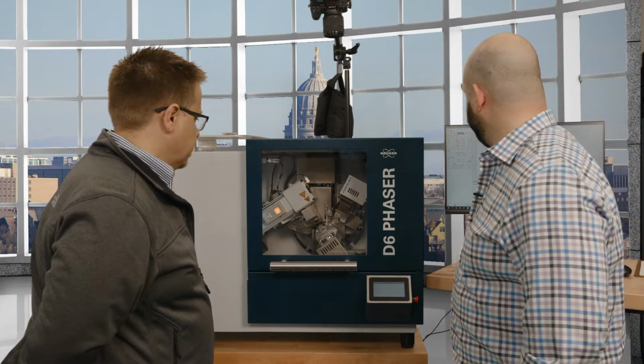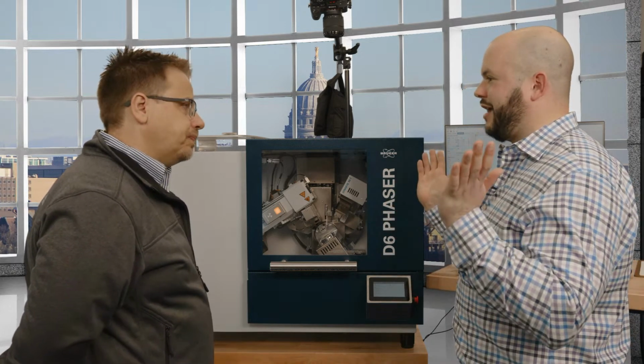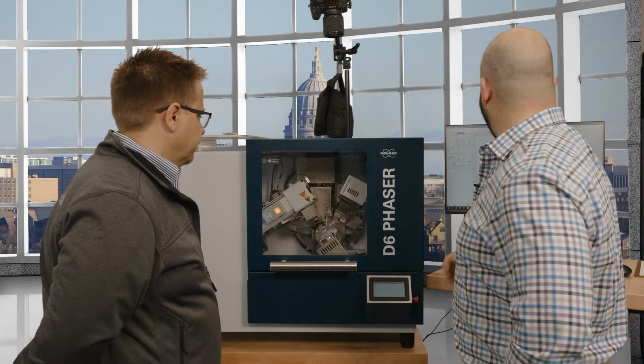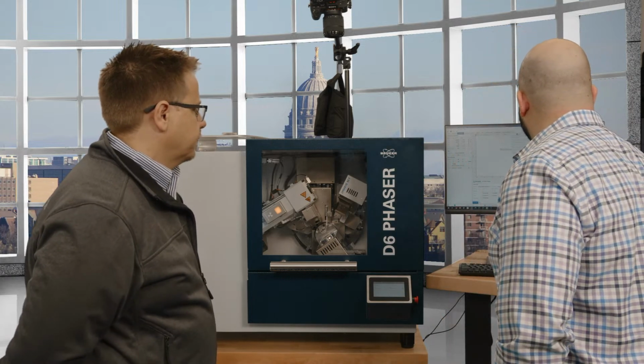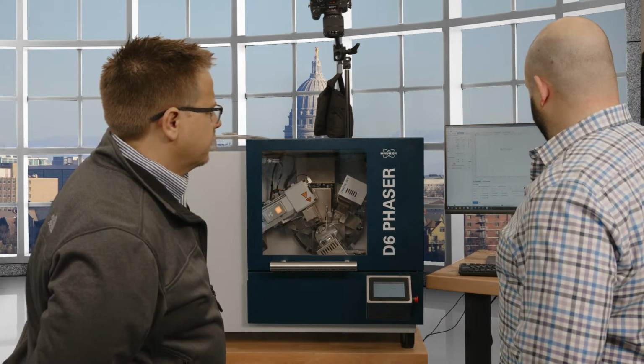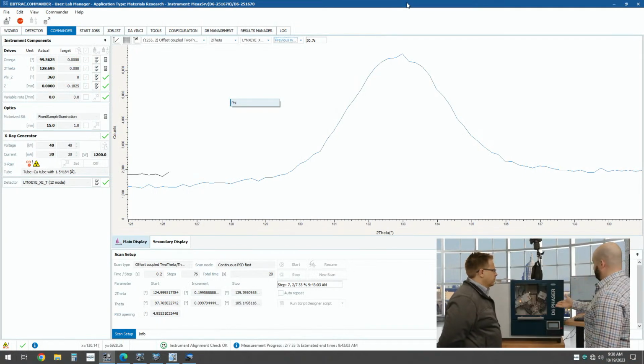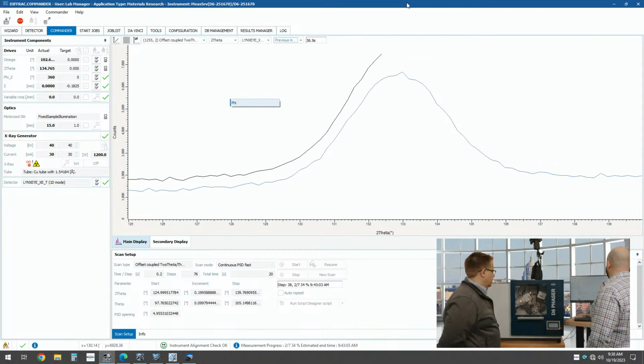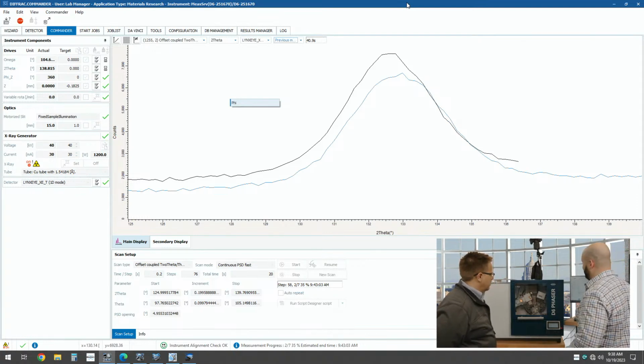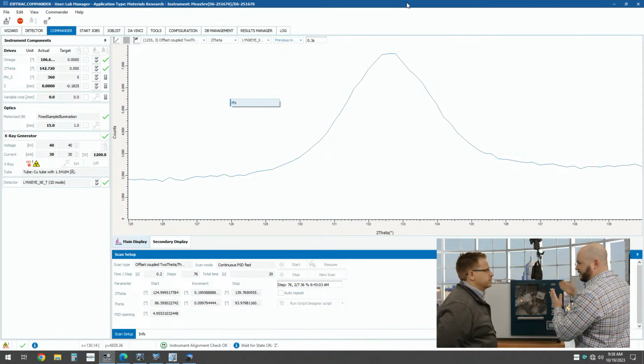Yes, that's correct. Okay. So it's almost like a powder type of scan, except now, if we kind of overlay this, so if we look at the previous measurement relative to a current measurement, you should see the center peak position shifting around. All right. Yeah, so you can see this peak is now to the left a little bit more. Oh yeah, definitely. Now that we're getting closer to the diffraction vector being parallel to the sample normal, I'm guessing this is a compressive stress.